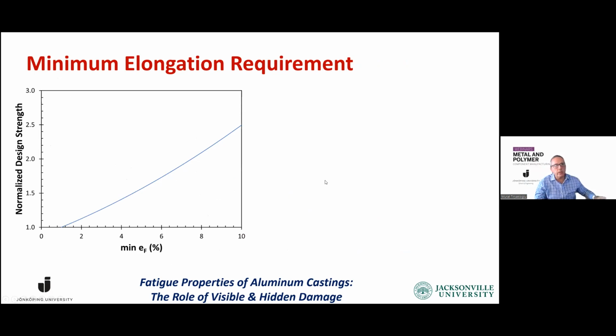So if you look at the normalized design strength with changing minimum elongation value, we can see this. If we go up from 1% to, let's say, 5%, the design value goes up about 60%. If we go to 10%, it goes up from 1 to 2.5. We can dramatically increase the design strength that we use for our aluminum castings.